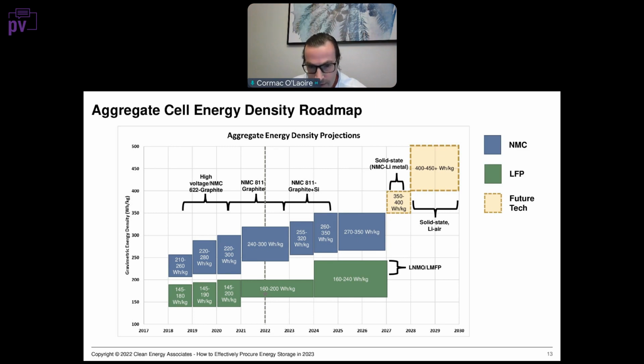The data we have here, for example, is for cell data. 200 watt hours per kilogram is advertised by certain LFP manufacturers, but as we know, that's not really accurate of the system in the field. What we're seeing in the field is cells at about 160 to 170 watt hours per kilogram or less, maybe even 150 to 170, depending. But we will see as we look out in the next 3 or 4 years that there will be an increase in the energy density of the BESS systems itself, using LFP or LFP variants, which we have highlighted here.